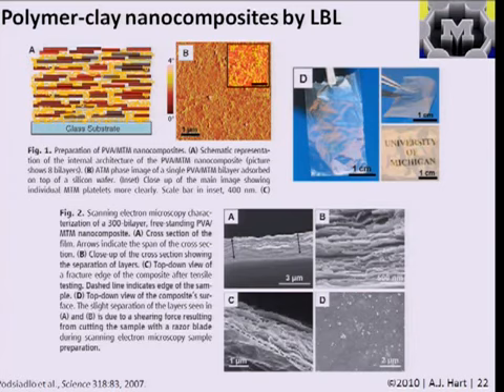And by doing this layer-by-layer process to create these structured layers, they were able to create the kind of nanoscale brick and mortar architecture that we saw as a biomimetic composite in the lecture on mechanical properties. Now we can compare the architecture of the layers made by LBL to the bottom right. These are SEM images of the cross-section of the composite. And we get an idea that there is this stratification or anisotropy of the sheets in the planar direction. These bilayers are maybe 10 nanometers or less thick, so it takes a very large number of bilayers to create even a film that's a few microns thick.